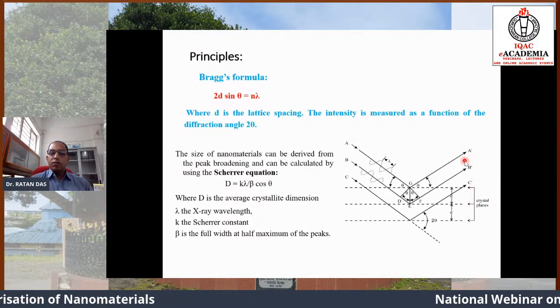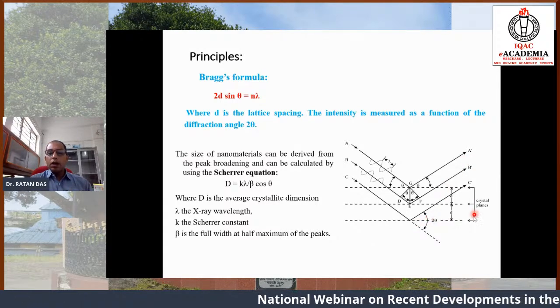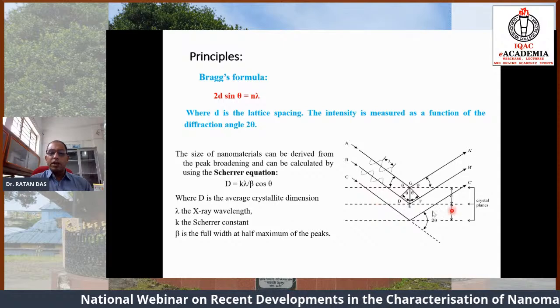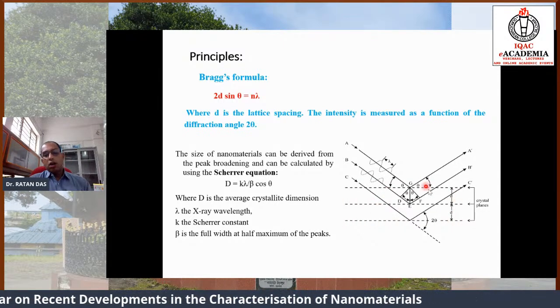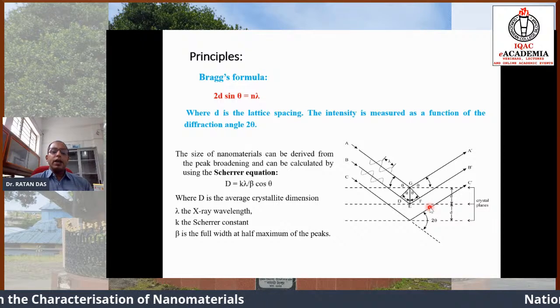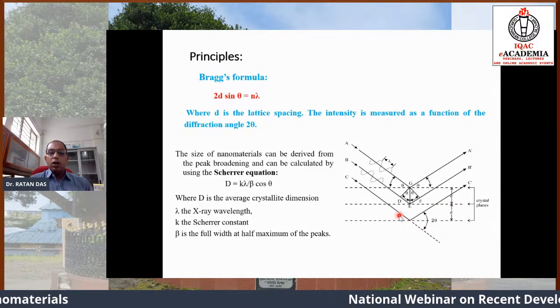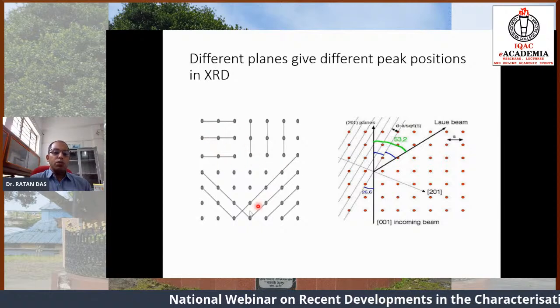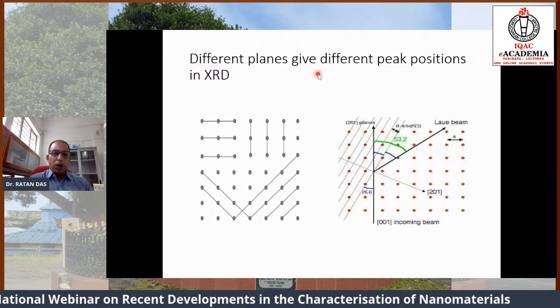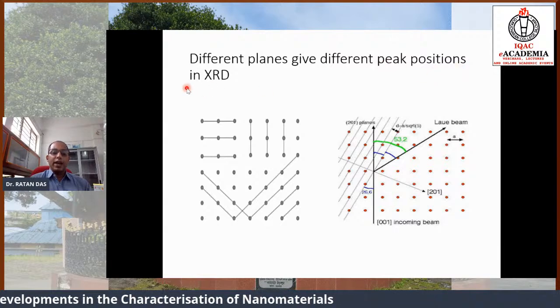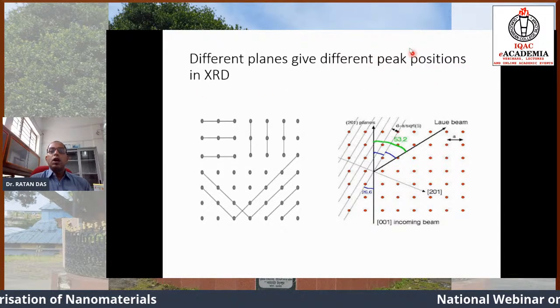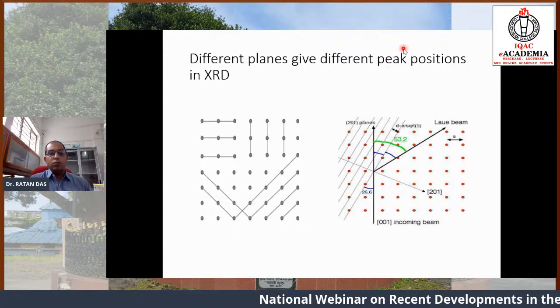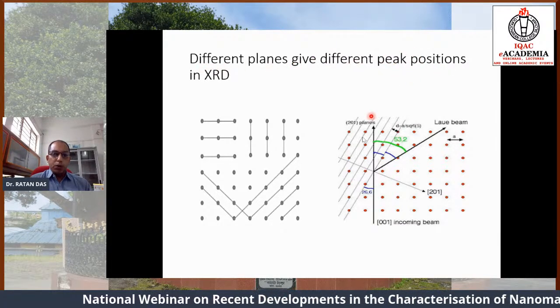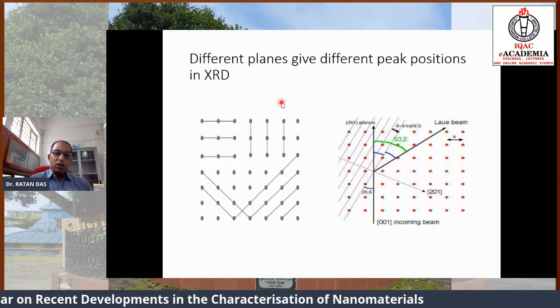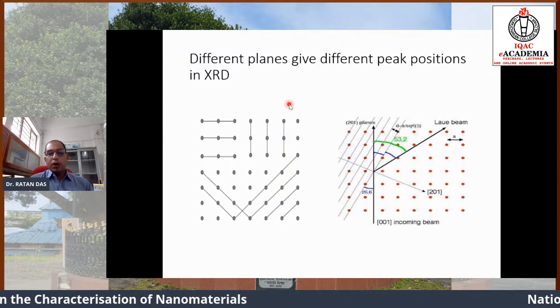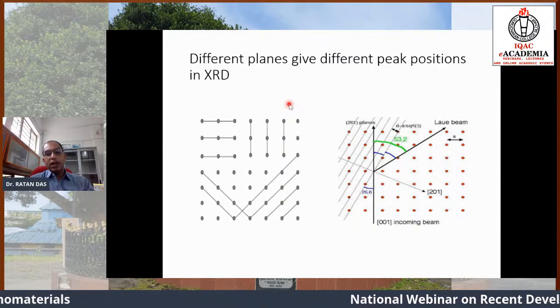Thereby we get the diffraction pattern at a particular angle, and it is not due to a single plane. If there is a single plane, then it is a single crystal structure. But in general, in a crystal we have many diffraction planes. Many planes will be available, as I have told you earlier. So different planes give different peak positions in the XRD. Peak position means where higher intensity of the diffraction pattern is available. Different planes give the diffraction pattern at different twice theta angles, and at a particular angle we shall get higher intensity.